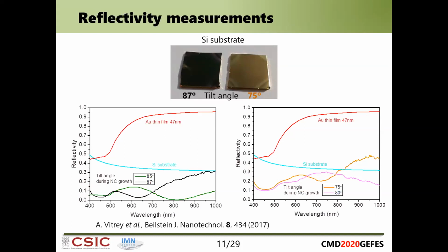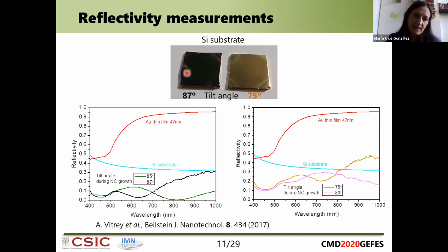So these films are very inhomogeneous, so it's difficult to do the simulations or to provide an interpretation or an analysis, because it's full of nanocolumns of different sizes, diameters, and everything. But what we understood from these things is that what is going on here is that we have nanocolumns that have localized plasmons, and when we have the system with a narrower distribution in diameters, but with a much higher distribution in heights, what is favored here is the light trapping. We have much more phenomena of multiple scattering, which at the end give rise to a much higher absorption of the light, and this is how we have the much darker, almost black gold here.